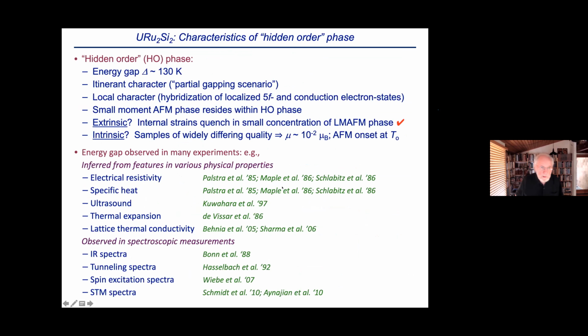Okay, so what do we know? Hidden order has an energy gap of about 130 Kelvin. It has itinerant character. I think you would infer that from the partial gapping scenario. It also has to have local character. These phenomena are driven by hybridization between the localized 5f and conduction electron states. The small moment antiferromagnetic phase resides within the hidden order phase, but that really seems to be a parasitic phase. It's extrinsic and due to these small strains that quench in the large moment antiferromagnetic phase throughout a small region of the volume. And then other measurements,